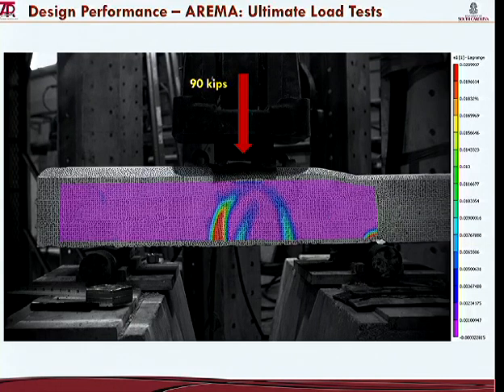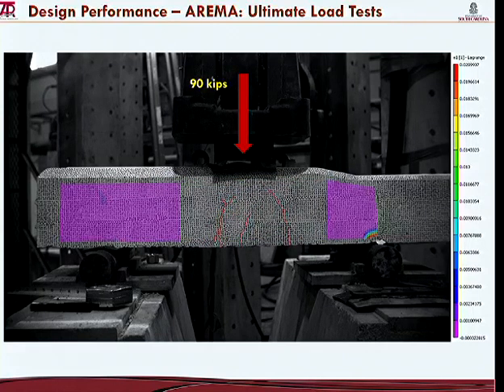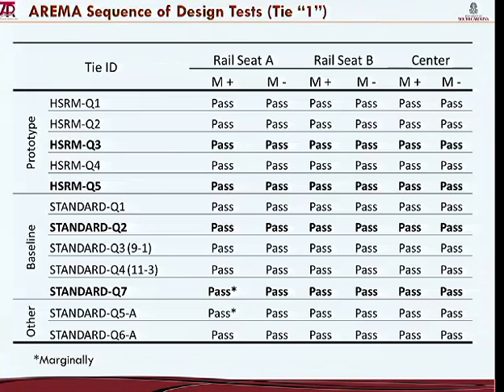At 90 kips load, which is approaching the design ultimate capacity, we see the cracks. We can clearly see the cracks developing on the tie. I just removed the color map, and these are the cracks indeed underneath. And we can do all sorts of things in actually measuring and tracking how these cracks open and close through the DIC measurements. Bottom line, the high performance, high strength reduced modulus ties all passed the qualification tests. The standard, there was one that marginally passed, and we were probably within 1% of the rail seat moment positive value.